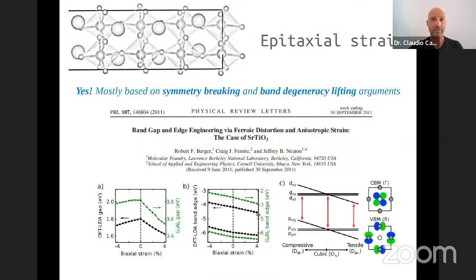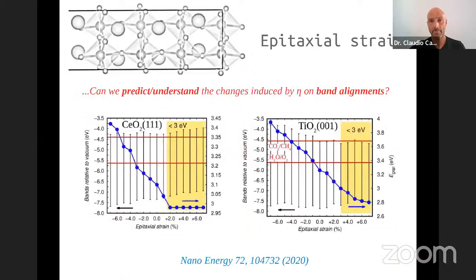This was, for instance, already shown by some people in strontium titanate, which is probably a more complex material than the two that I've shown. They showed how symmetry breaking was important in understanding these effects, right? Of course, that was not, in our case, the only effect to take into consideration. On the compressive side, we also had to resort to electric screening arguments in order to understand why the gap was increasing up to here, right? But pretty much, these symmetry arguments can be very useful to understand the evolution of the band gap, right?